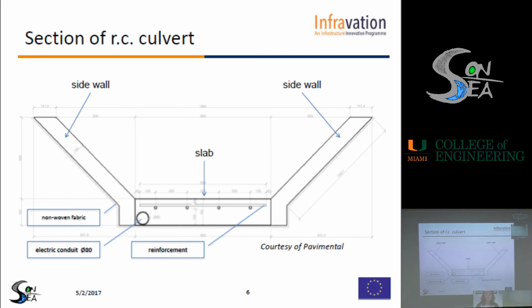This is the section of the culvert. The culvert is made of a slab that lays on the soil that is about 80 centimeters wide and 15 centimeters thick, and it is reinforced, and it is surrounded by 2 inclined side walls that are non-reinforced, and they are made with ordinary concrete. The reinforcement is in the form of a mesh with spacing of 20 centimeters, and the thickness of the concrete cover of all the reinforcement is 30 millimeters.